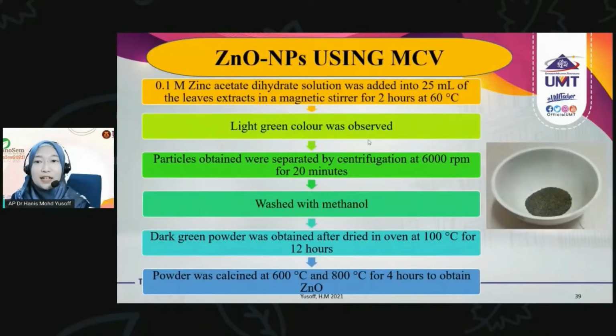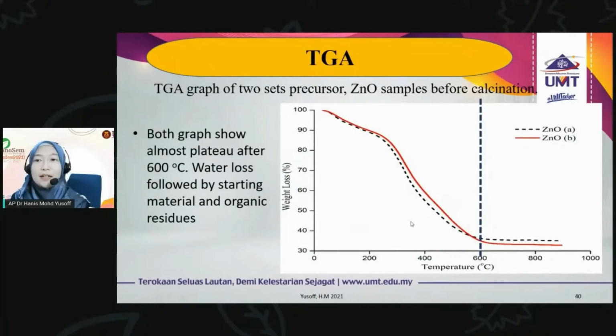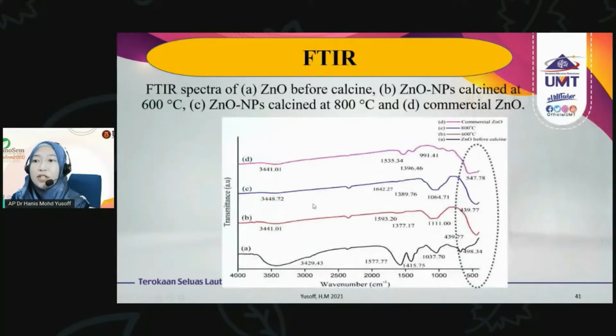Okay, to the last one, zinc oxide nanoparticles. So this was the method used. Then, of course, the main thing is to monitor with TGA. So a similar pattern, only the plateau here is a bit higher than magnesium oxide. So then the calcination temperature started at 600 and also 800. So for zinc oxide, the adsorbed water molecule is not as obvious as in magnesium oxide. Okay, so you can see the decrease here.